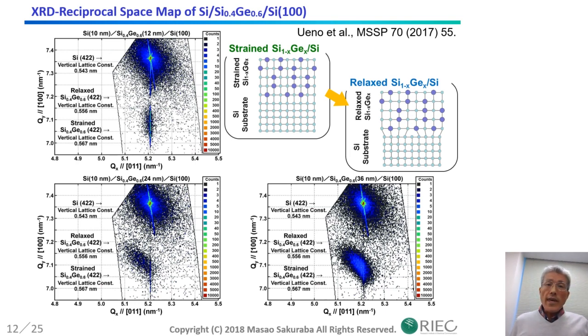These figures show XRD reciprocal space maps from silicon-silicon germanium alloy heterostructure on silicon substrate. The line-shape diffraction pattern is aligned to the silicon substrate position, and this indicates the silicon germanium alloy is lattice matched to the silicon substrate. For films thicker than 24 nanometers, the diffraction pattern tends to shift and to be diffused. This indicates the film strain becomes relaxed. This trend is not so different from the case of conventional thermal CVD.